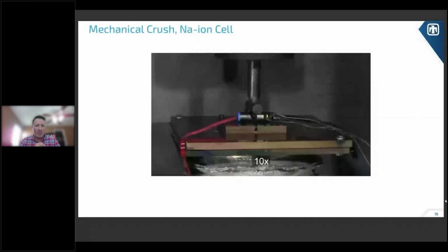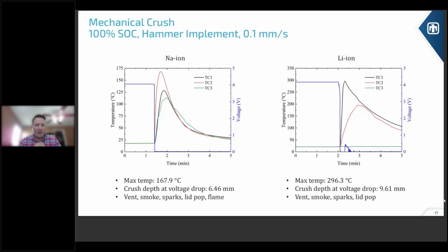So as you can see, it's kind of a similar response to the nail penetration. The hammer implement was holding the cell in place, so it didn't remove itself from the fixturing. But you got a similar response, that kind of rapid pressure increase that blows the lid of the can off. And then you also saw that there was a smoldering ember next to the cell, and that actually caught the vent gases on fire. So they are flammable under the right conditions, which we would expect because, as I said previously, it is a mixture of typical organic solvents that you would see even in a lithium-ion battery.